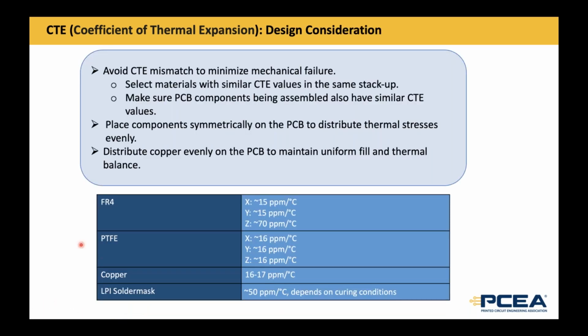next slide here. What are some of the things that you want to consider for design? And I'm sure those of you who are on this webinar that have designed PCBs come across this topic a lot, CTE mismatch, and I hear that a lot too. So you really want to avoid CTE mismatch to eliminate mechanical failures. Rule of thumb is to select materials with similar CTE values in the same stack up. Don't use materials that have a lot of different CTE values. And this goes the same as well for components that are being assembled on the board. Make sure they have similar CTE values.